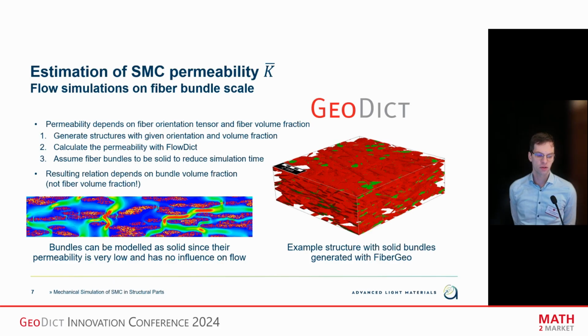And what you see here on the left of the slide is, in the beginning we started with structures where the fibers were resolved, but then it turns out that the permeability within the fibers is very low, and the main flow is always between the bundles. Therefore, we use structures where the fiber bundles are modeled as solid, and thereby we could reduce the simulation time a lot. Otherwise, it would actually not be possible to perform such a study.